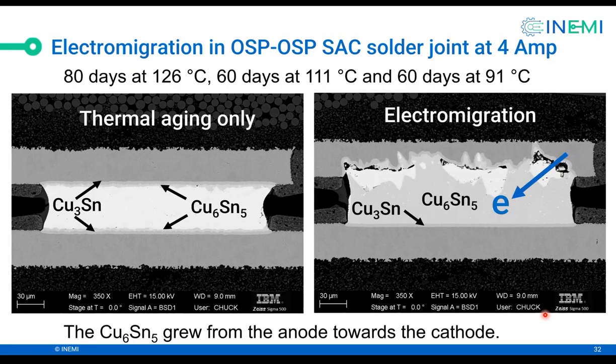So now what happens when you pass current? The plot on the left is just thermal aging. There is no current. The one on the right, electrons flow down this way. And notice the huge difference between the two. So what happened in this case is that the copper in the top metallization dissolved and electromigrated into the tin, and it formed this intermetallic which grew from the anode towards the cathode. And it almost completely consumed the solder.